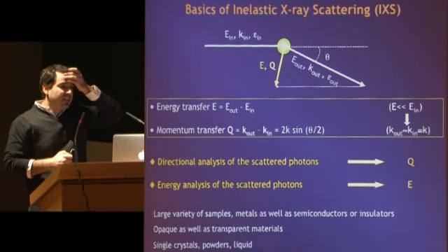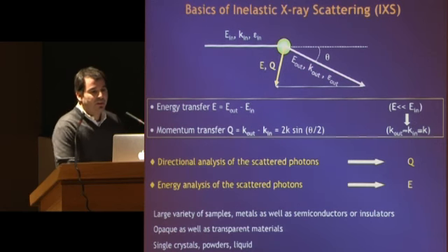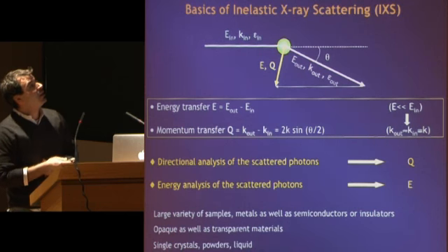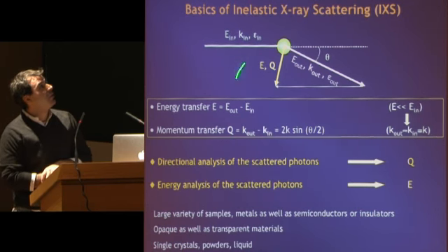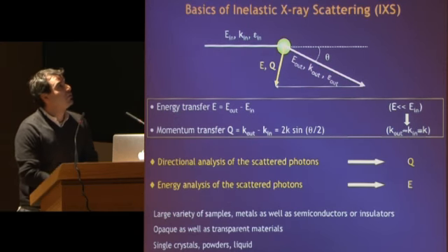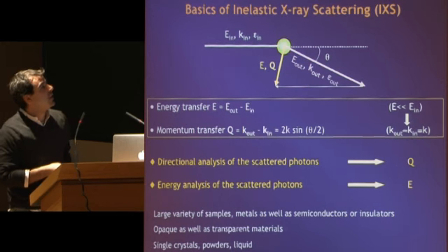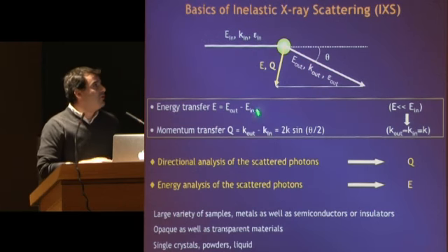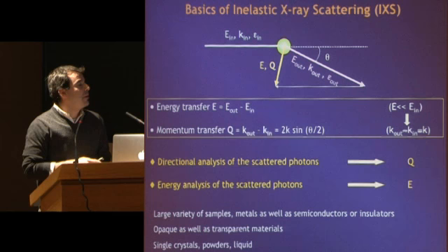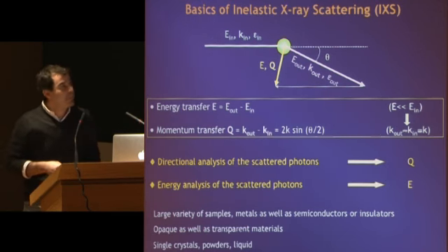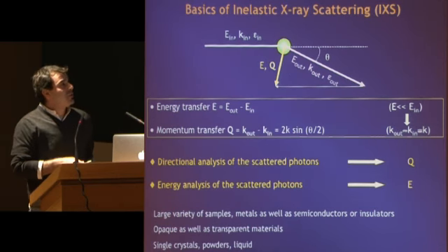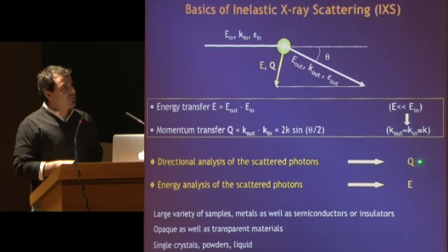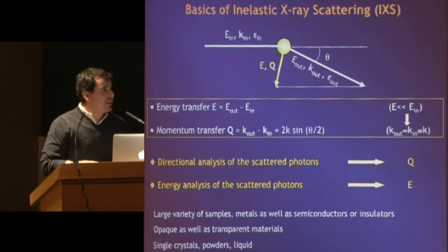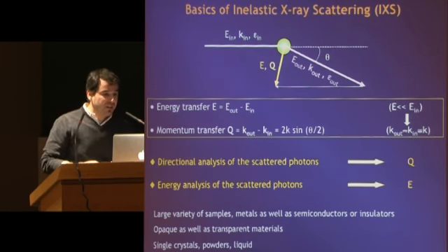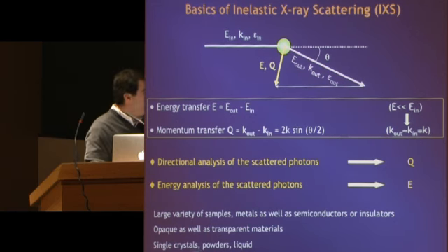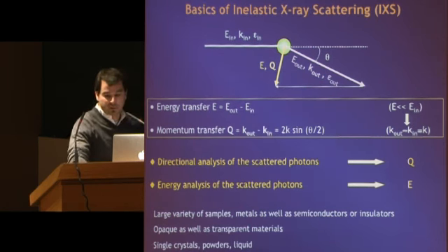The other technique, inelastic X-ray scattering, is a conceptually simple technique. It's a photon in, photon out technique where a photon of well-defined energy, momentum, and polarization is scattered by the sample into a second photon of well-defined energy, momentum, and polarization. And given the energy and momentum conservation laws, the difference between the outcoming and incoming energy and between outcoming and incoming momentum is the energy and momentum transferred to the system. So basically, performing a directional analysis of the scattered photon relative to the scattering angle, we can get information on Q, and from the analysis of the scattered photon, the energy E. This technique can be applied to a large variety of samples, be this metal or semiconductor, opaque or transparent, be this single crystal, powder, or liquid.